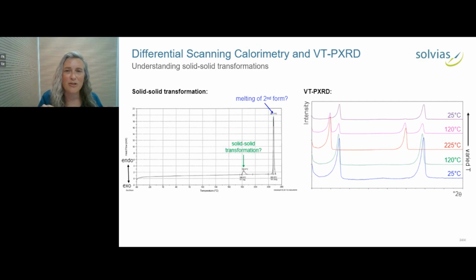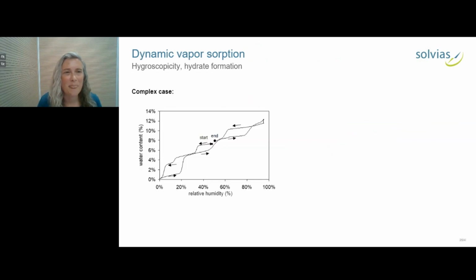As you lower the temperature to 120, you see a mixture of the forms. And finally, going back down to room temperature, you're essentially back at the initial form. So in this case, the high temperature form was not very kinetically stable, but nonetheless, we were able to confirm that we understood what was happening in the DSC.